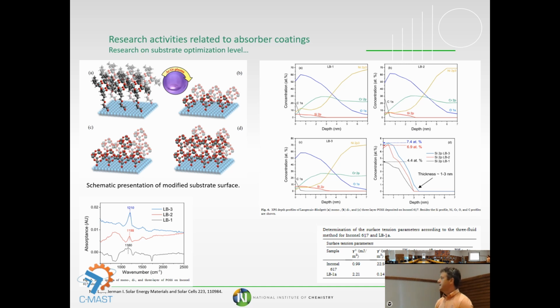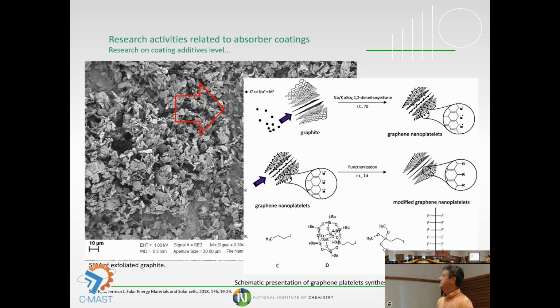So we tried to apply the black color in a second layer, and for sure we faced problems with adhesion and so on. So then we tried to do some modification with additives for high temperature, maybe less, just because at 500 most of the carbon-based material in an air atmosphere is burning out.